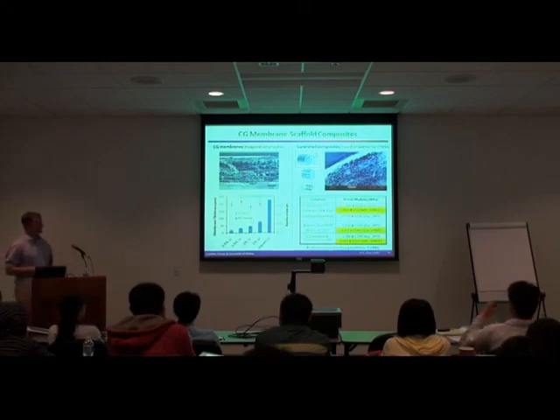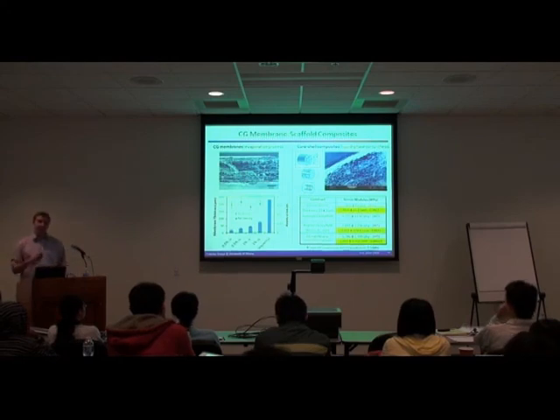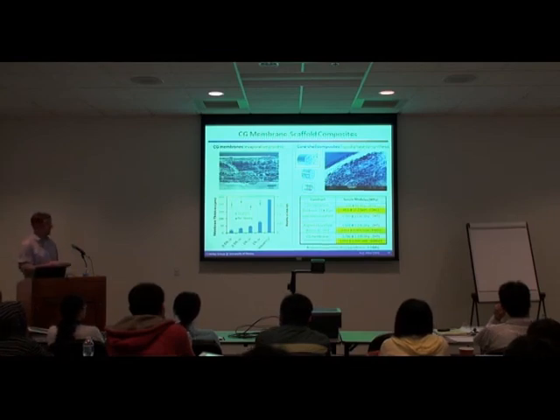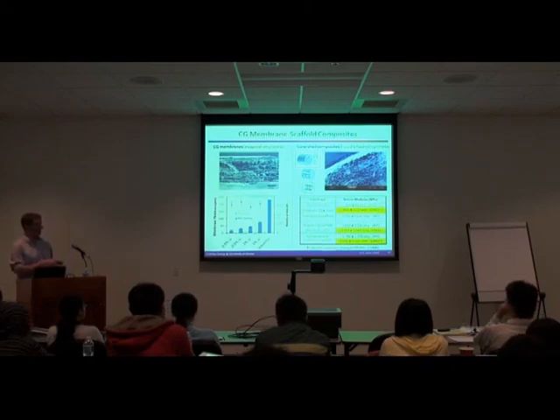But there's actually a really nice modeling system we could use. We have our cellular solids modeling to give us a sense of how the scaffold structure and mechanics change as we affect relative density or pore size or cell alignment, those sorts of things. And then there's the idea of layered composite theory, which does a very good job of predicting, if we have a membrane of a certain dimension and stiffness and a scaffold of a certain dimension and stiffness, what our composite will be quite accurately.